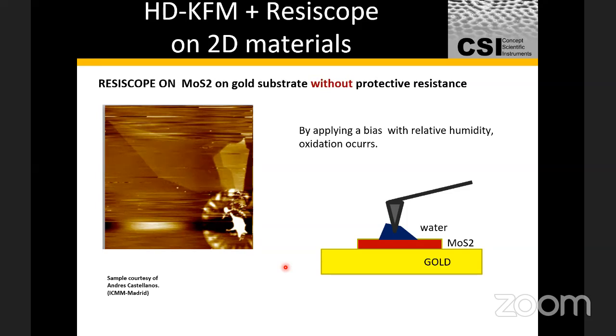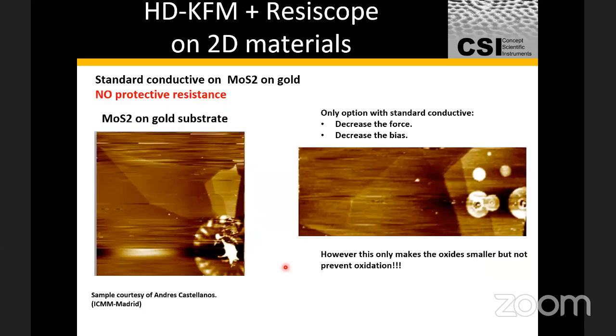Yeah. So that's what I was trying to illustrate here, and I guess decreased. And these are just telling you, in a standard technique, in a standard AFM, you don't have really a lot of choices. You could only try to reduce the physical interaction by reducing the force on the tip, or decreasing the bias, maybe to reduce the current. But this will only make the oxide smaller, and not prevent the oxidation.